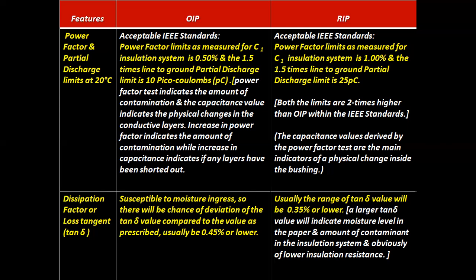Acceptable IEEE standards for RIP bushings: power factor limit as measured for the C1 insulation system is 1%, and the 1.5 times line to ground partial discharge limit is 25 picocoulombs. Both limits are 2 times higher than OIP within the IEEE standards. The capacitance value derived by the power factor test is the main indicator of a physical change inside the bushings.